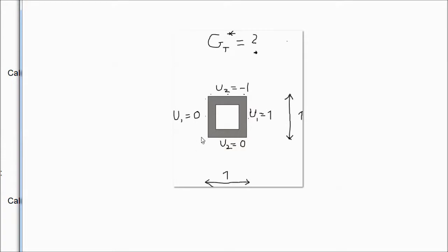Here we have it. Then I use the displacement. I put the displacement on the left hand side in the x direction. That means u1, I put it equal to 0. So I fix the values on this boundary in the x direction. On the other vertical boundary, I put u1 equal to 1.